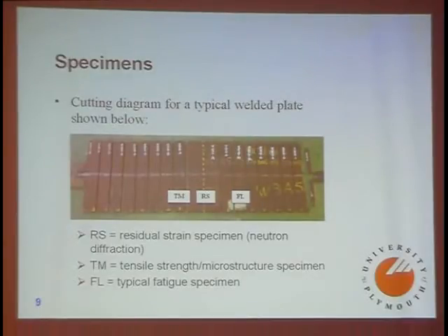And one of the things that Corus had shown originally in previous work was that if you had the same welds fabricated by 2 or 3 people and then stress relieved as well, some of them, you ended up with completely different sets of fatigue data. And it got worse as the strength of steel went up. They said, we don't really know what this is. We've done some residual stress measurements. They didn't explain this at all. They gave a counter result. And at this point I came along and said, in exchange for only a small sum of money, we can run a PhD project. This is it.